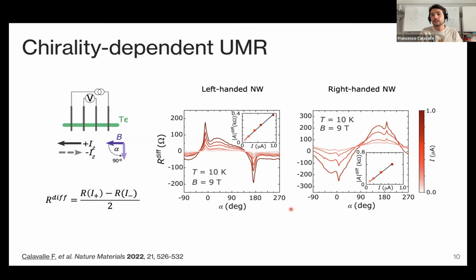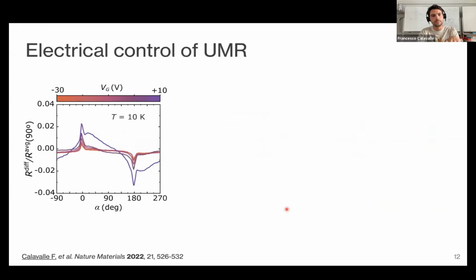And this, indeed, changes from sample to sample, and we think that it depends on the Fermi energy position, because we notice that depending on the thickness of the nanowire, we have more or less self-doping. So the starting point is always different. And if you look at the gating here, you see that in this sample we had almost a flat curve and only these spikes here.